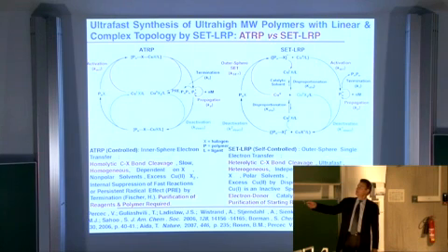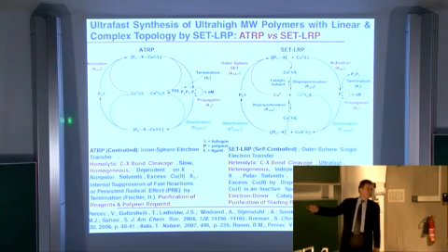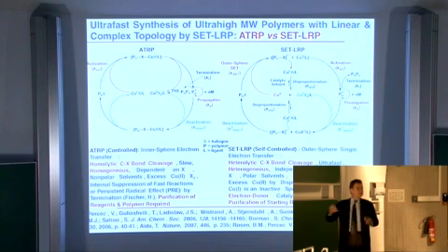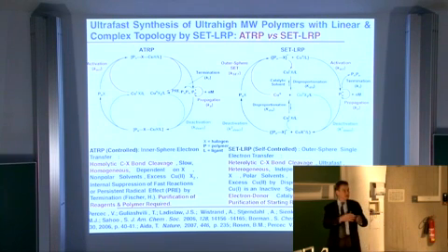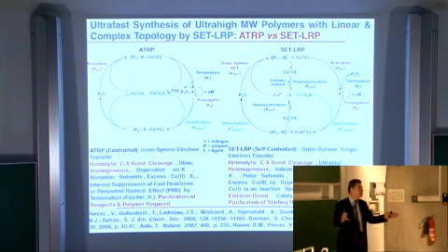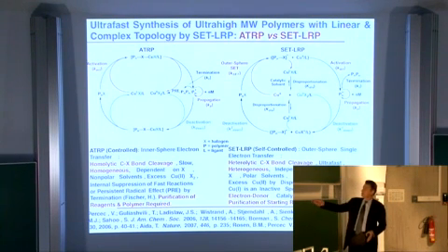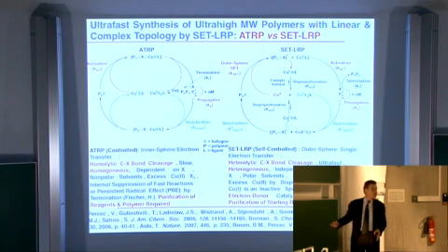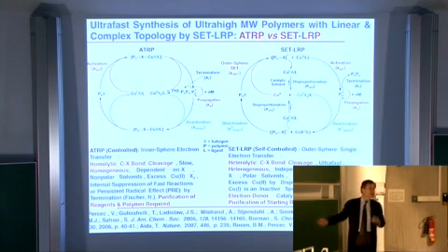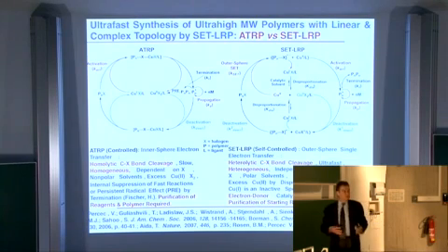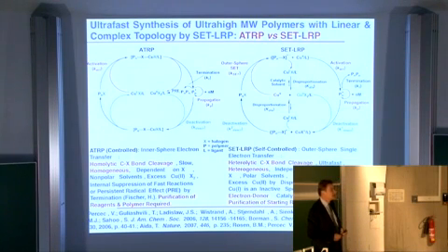The copper-2 reagent that is generated in this step shifts the equilibrium towards the alkyl halide, but this requires a little bit of one of the fastest and least desirable reactions to take place, that is bimolecular radical termination. If you get a little bit of bimolecular radical termination here, you get an increase in the amount of copper-2, and that shifts the equilibrium towards this species, and very few radicals exist. And that can provide a very high chemoselectivity.